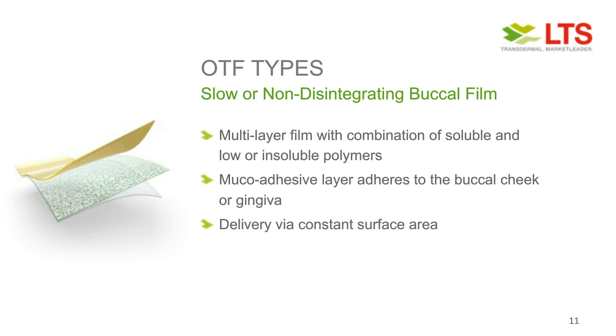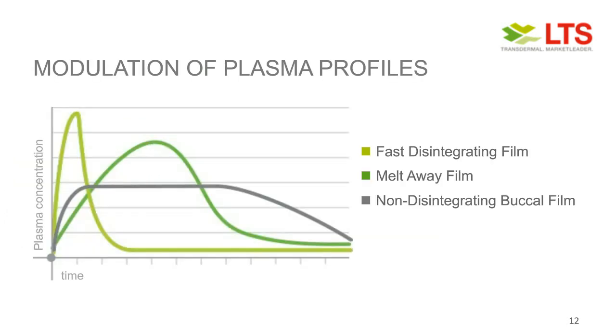So we are delivering the API via constant surface areas, really like a patch, but of course the time where this is applied is not comparable with the transdermal systems. We're talking here anything in the lower hour range at most, if it's possible at all. So these three types of our thin films end up in different types of plasma profiles which we can achieve, which we can tailor and modulate as it's needed for the API and for the indication.